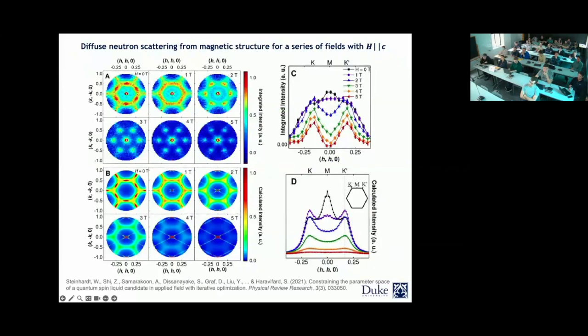So here what I'm showing you is neutron scattering data integrated over energy, and you're looking at the Q space. This is at zero field, and these are all done at millikelvin temperature. So we are in the quantum mechanical regime, and you don't have a lot of thermal fluctuations. You can see the zone boundaries, and at high symmetry M points, and the K points at the corners, you're getting more excitations, and you can also track the zone boundaries very well with additional excitations at zero field.